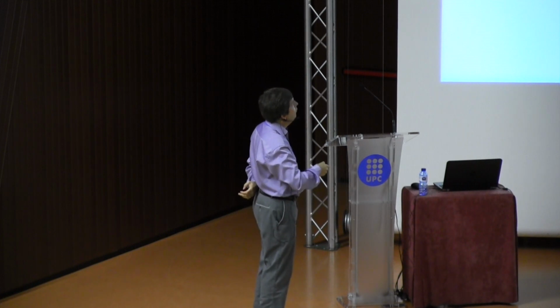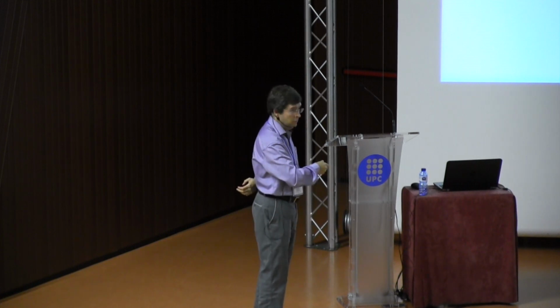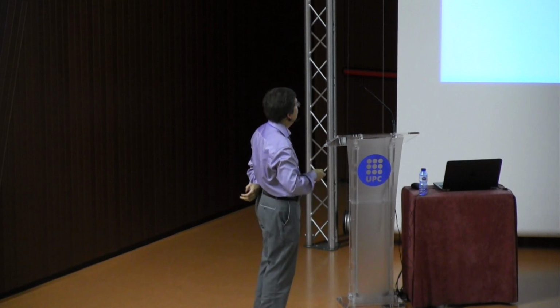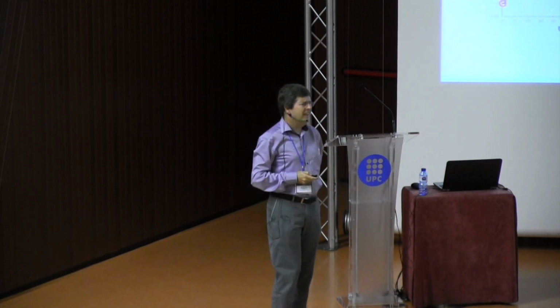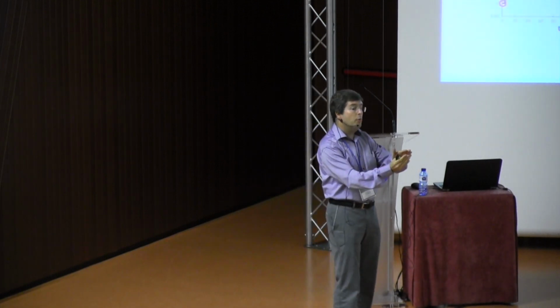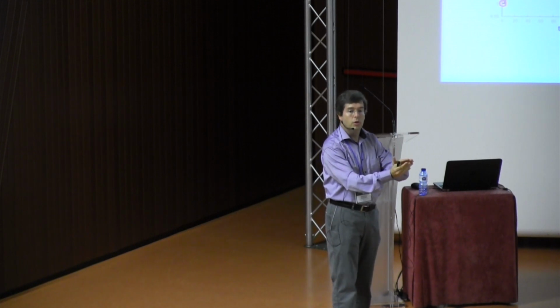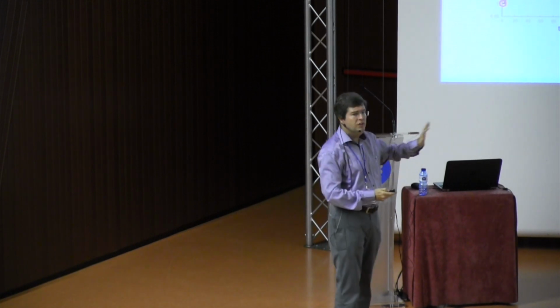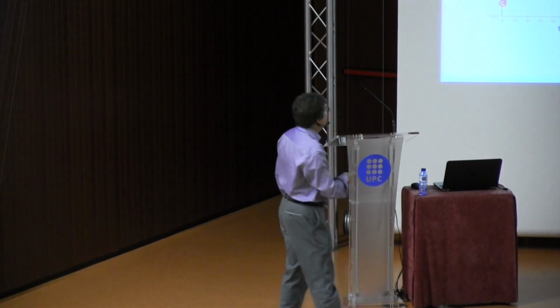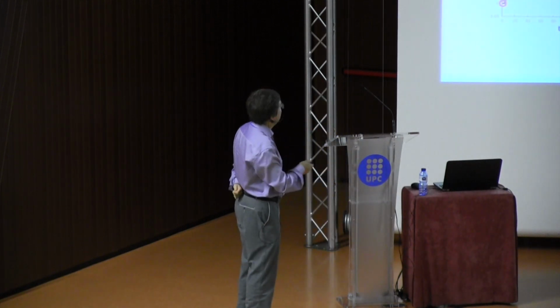And the threshold depends on the accumulated slip, and under cyclic loading for instance, you have to take care because at the crack tip you may have opening, but you may have closure also. So you have to take care of some unilateral effects.